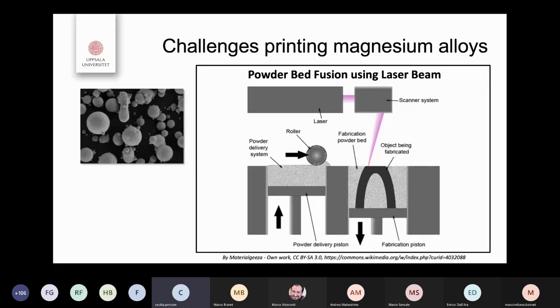One of the most promising methods for printing magnesium alloys is powder bed fusion using a laser beam. So you see an example of magnesium powder to the left here, and you've probably seen this, but what you do is you melt one layer of powder at a time so that you get the object that you desire.